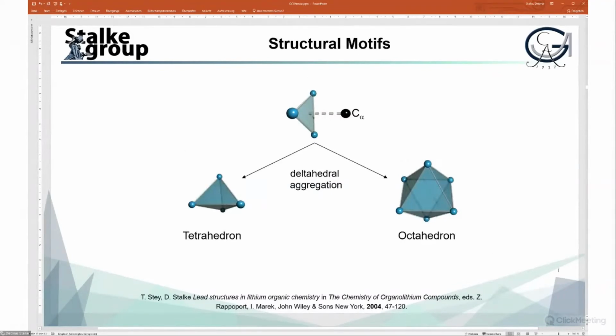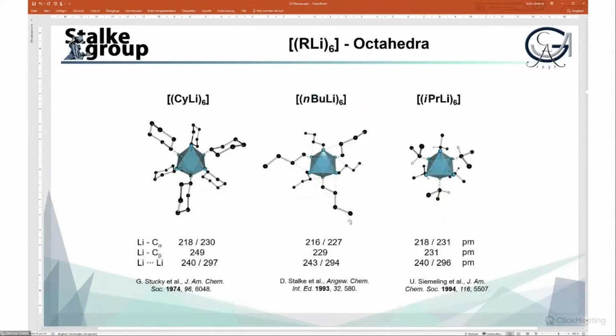If we look at the structures of lithium organics, we have an overarching structural motif: a triangle of lithium cations bridged mu3 by a deprotonated or methylated C-alpha from any organic residue. This motif, like Lego, can be put together in deltahedral aggregation to form a tetrahedron or an octahedron. This is the motif in lithium organic chemistry.